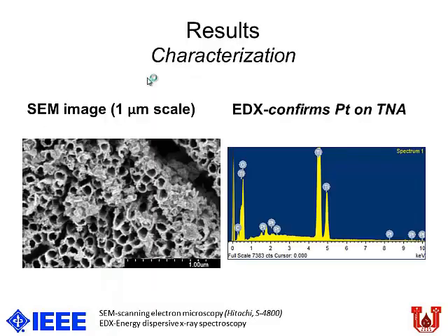This is the SEM image at a 1 micron scale. So you can see the tubes, pretty uniform diameter holes, and the stuff that's right here that looks like dirt is platinum that's deposited on your tubes. To confirm the deposition of platinum on the titania nanotubes, we ran an EDAX on it. That's energy dispersive X-ray. So you can see the presence of platinum on the material along with titanium and oxide. There's also a little bit of carbon, which is unique to the method we made it.